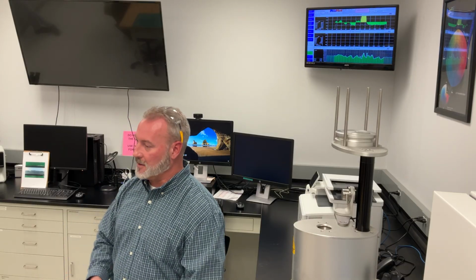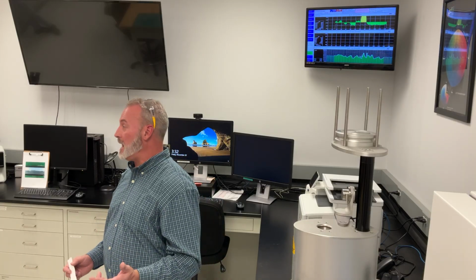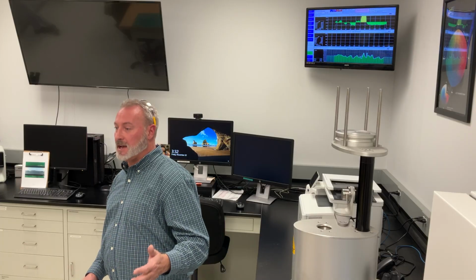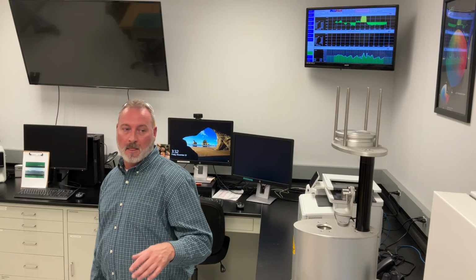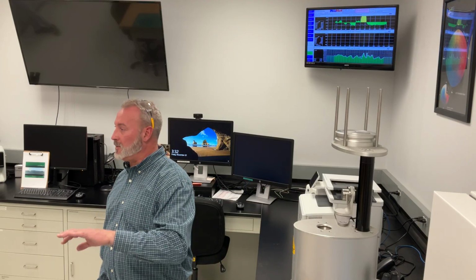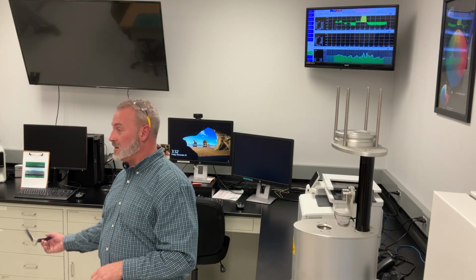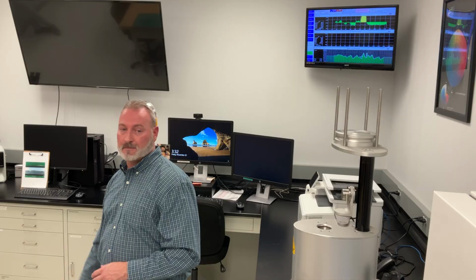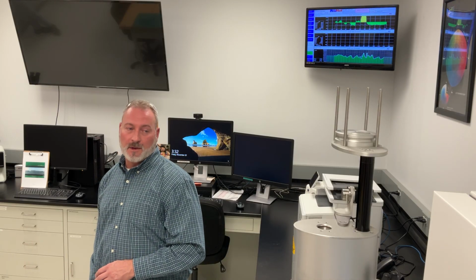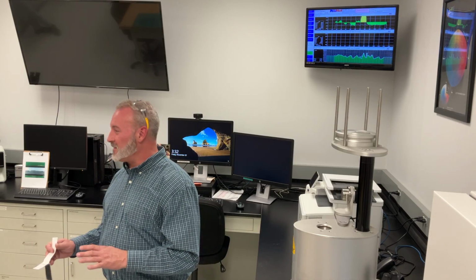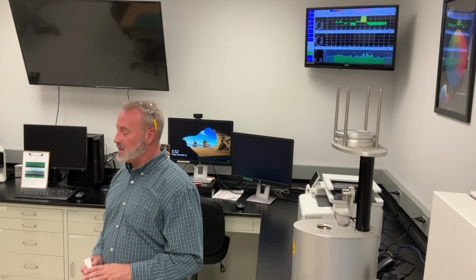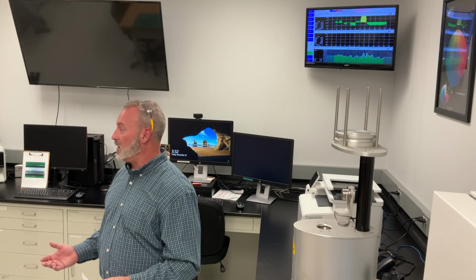And it's a 3-inch mandrel, just a pipe, right? We bend it over it, look at it under a magnifying glass again, and it has to pass both of those things in order to consider a pass, right? So the 56 day is the ASTM minimum. Internally, we keep other samples in there for 70 days for GAF1, GAF4, 90 days for GAF Extreme, right? And if we don't pass the internal spec, we don't get real excited about it, but if we don't pass that 56 day, we know something's going on.